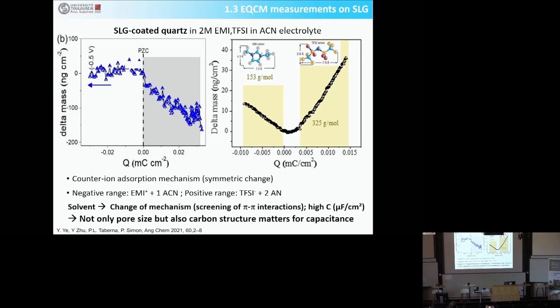When you add acetonitrile as a solvent to EMI-TFSI, you completely change the ionic flux onto the graphene. From the PZC, when you inject positive charge you only see weight increase from anion adsorption — and when you inject negative charge you only see weight increase from cation adsorption. This is a huge change in the charge storage mechanism due to charge screening by the solvent. As a conclusion, the pore size is important for increasing the capacitance, but the local structure of the carbon — specifically sp2 carbon — is also super important.